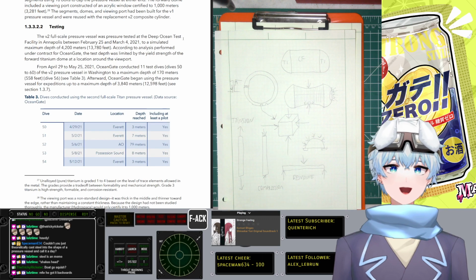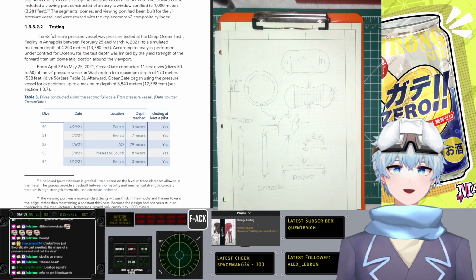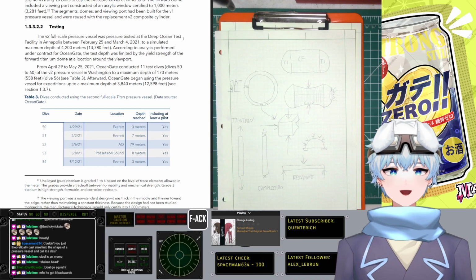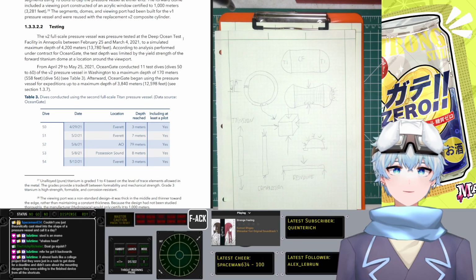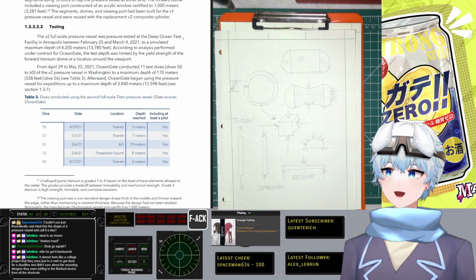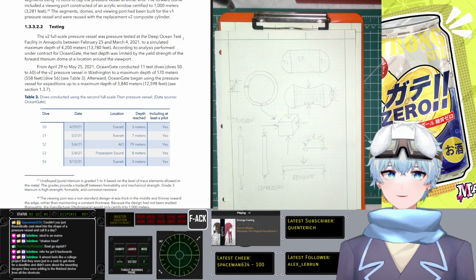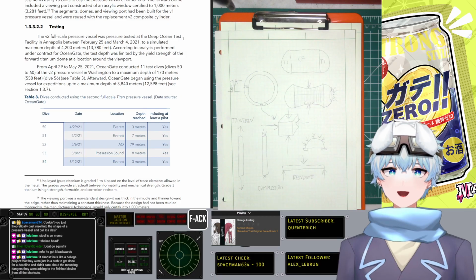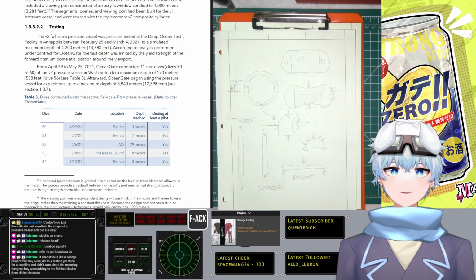The V2 full-scale pressure vessel was pressure tested at the Deep Ocean Test Facility, simulated maximum depth of 4,200 meters. According to the analysis performed under contract, depth was limited by the yield strength of the forward titanium dome at a location around the viewport. Now that I don't really like, because you can't really get a very good safety factor in this.